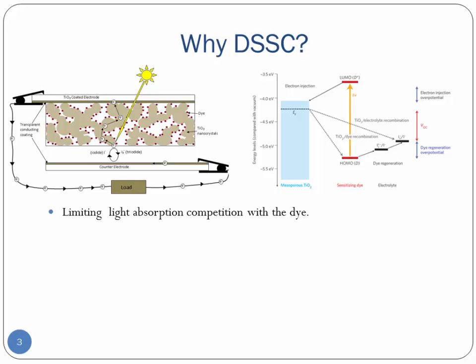For example, everybody knows that carbon nanotubes are black, so they absorb the light and they compete with the dye for light absorption. So if, instead of using mixed carbon nanotubes, we use single chirality carbon nanotubes, we reduce the absorption from a broad band to specific absorption peaks. So the efficiency is supposed to be increased.